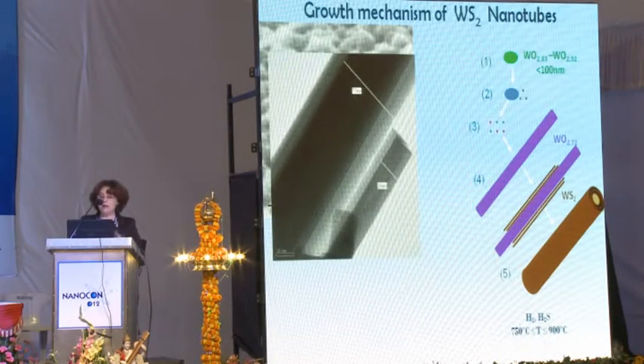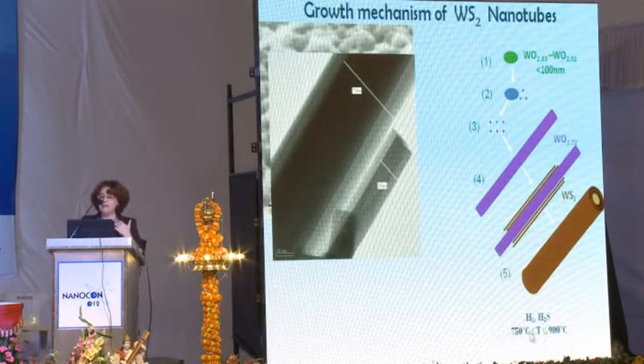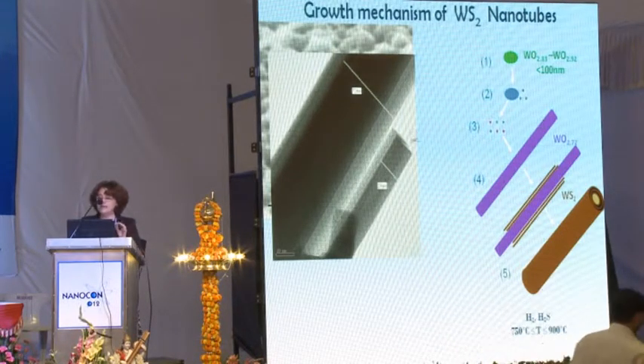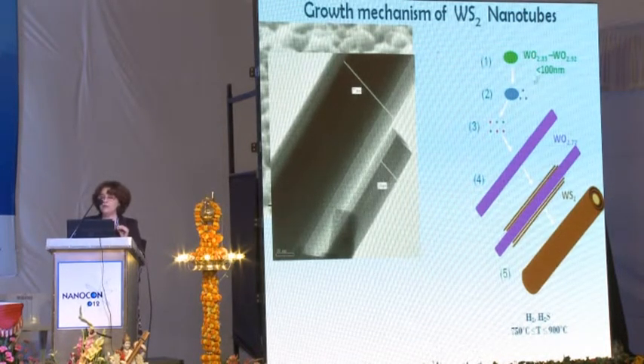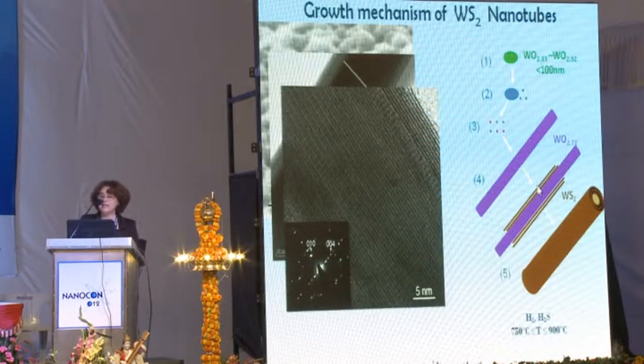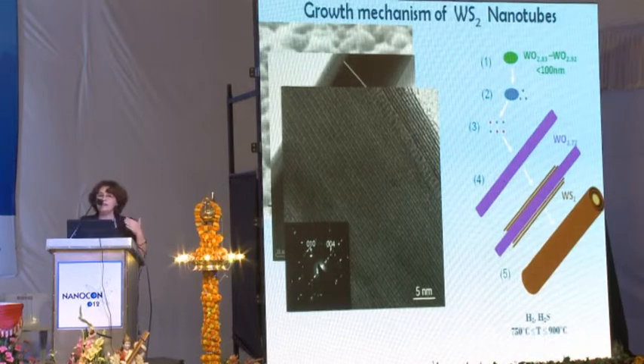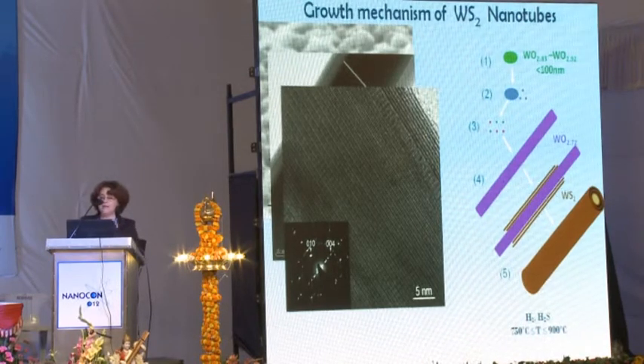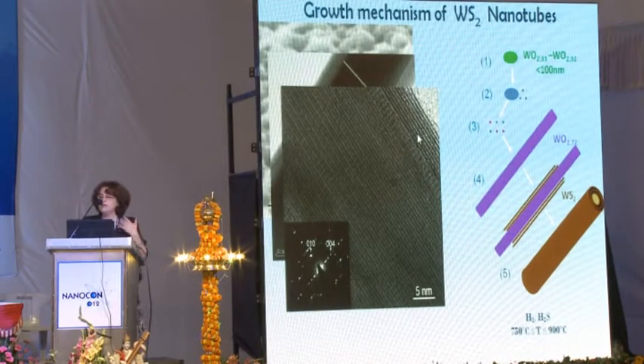Then you put this powder into the reactor. In the reactor, at 750 to 900 degrees in the presence of hydrogen and hydrogen sulfide, in a few minutes you see the growth of long nanowhiskers of tungsten suboxide, already a slightly more reduced phase compared to the initial one. After 5 minutes the sulfidization starts, and we can see a few layers on the external surface of the nanotubes.